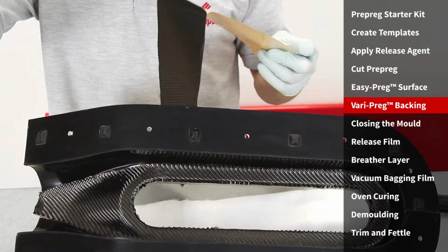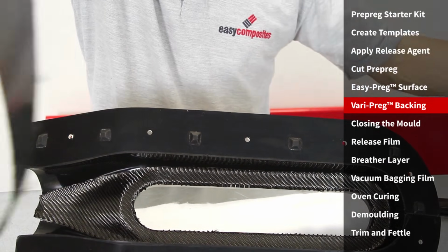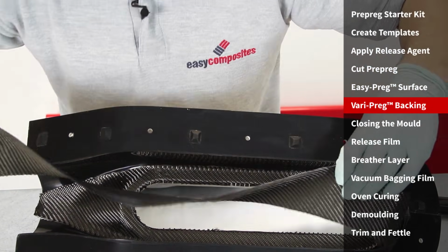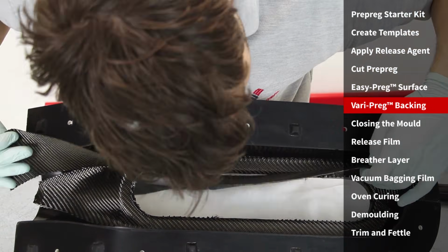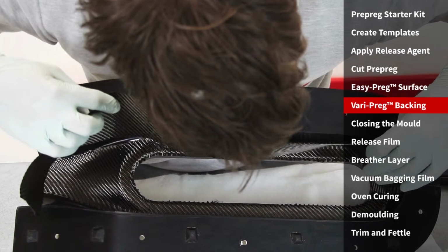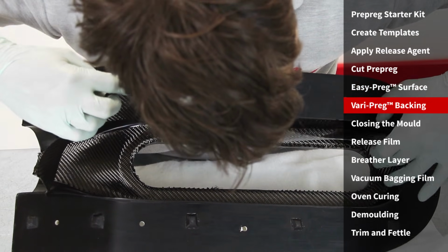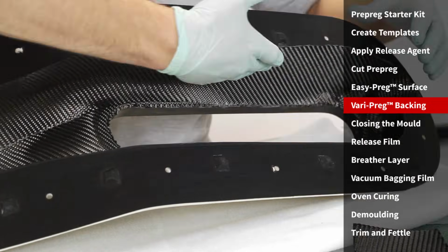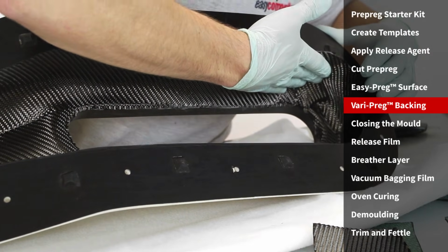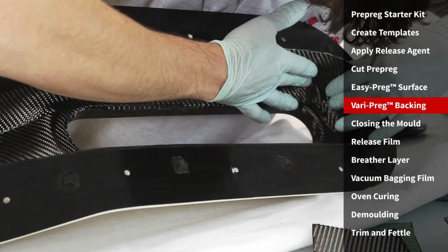The side pieces are then placed into the mould. If you remember, these are cut slightly larger to allow for overlap onto the first piece. In the case of this part, the overlap of around about 10mm will provide a strong joint. When curing, the resin will flow around this joint, making a seamless finish at the point of overlap.